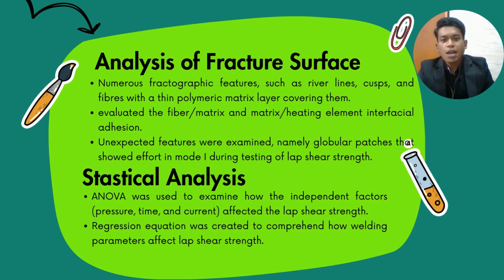In addition, analysis of the fracture surface. Numerous fractographic features such as river lines, cusps, and fibers with a thin polymeric matrix layer covering them. Evaluate the fiber and matrix and matrix and heating element interfacial adhesion. Unexpected features were examined, namely globular patches that show effort in mode during testing of lap shear strength.